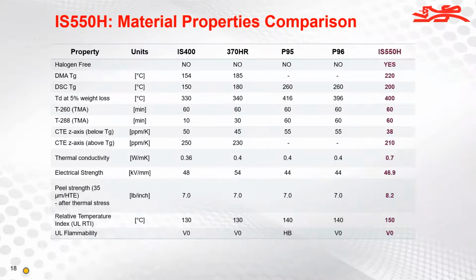It's a high TG material. I guess you could say it's one of the highest, if not the highest, TG material that's not polyimide or a polyimide blend. And again, this resin chemistry is very different than what has been traditionally used in PCB, but more common in the composites industry, areas where there is extreme temperature cycling and they need material to stand up. We can also provide more detail with the technical data sheets, which you can get by reaching out to Isola or Insulectro. We can get you some more data on that: the Dk/Df charts, all the usual sources for information on the materials.